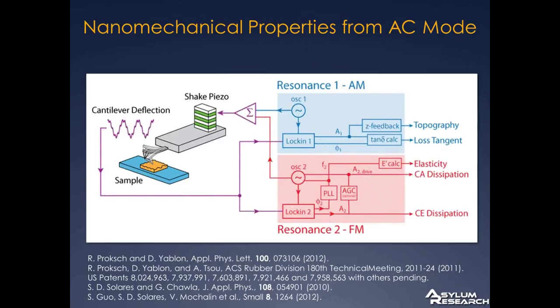Now a second mode can also be excited at the same time. We do that with the same kind of setup. We have an oscillator here, and we sum that voltage into the shake piezo. Now the response, instead of just being a simple sine wave, is a sine wave with a tiny little extra sine wave on top. That's that second resonant mode.